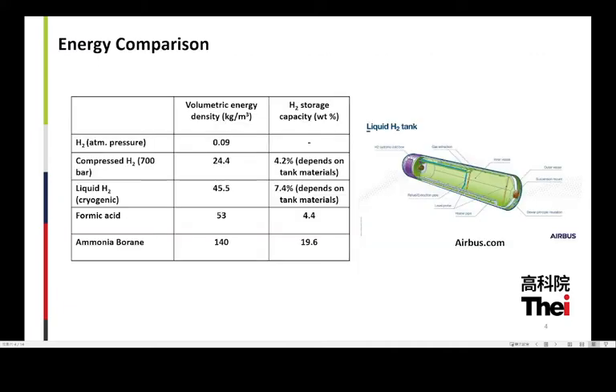Hydrogen can be stored in different states, like air in atmosphere, compressed gas, liquid hydrogen, formic acid, and borane material, like ammonia borane. In this table, ammonia borane has the highest volumetric energy density, which is about 140, and the storage capacity, 19.6, and that's why we choose it as our hydrogen storage material.